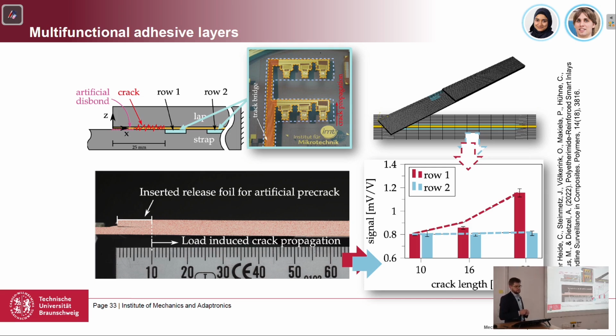One more slide on the multifunctional adhesive layer. So we have here a side view or cross section again from the bonded structure. Here is the bond line in the middle. We have two rows of these multifunctional elements made from PVDF and the CFRP structure. And you can see here from above the sensor structure made by the Institute of Microtechnology from our university. And then we performed this kind of test, which is a crack-lap shear test. You apply a tension load on both ends, and then a crack grows in the bond line.